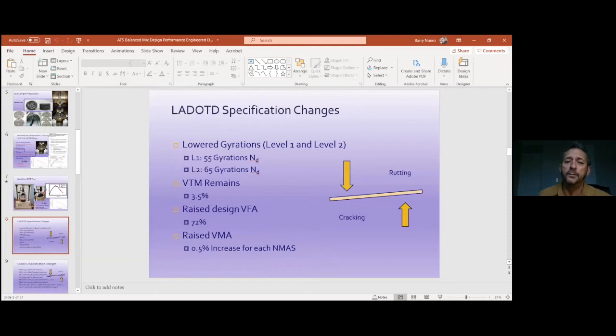And if they do look at 4% air voids and have volumetric requirements, then let's just say your balanced mix design moves you to a 3.6% air void or a 3.7% air void, well, then they'll give you plus or minus 1% off of that. So in Louisiana, we're already at 3.5. We've held on to that. They raised the VFA. I think that helped us quite a bit because we've had a lot of mixes that really met this spec. And I'll go ahead and say it here.